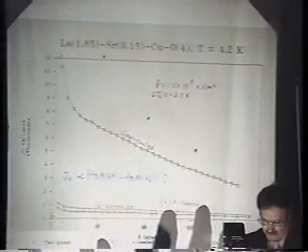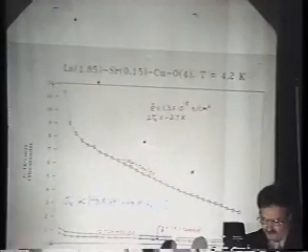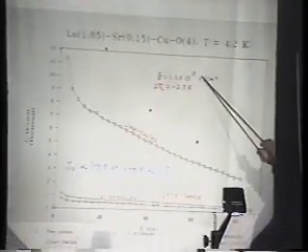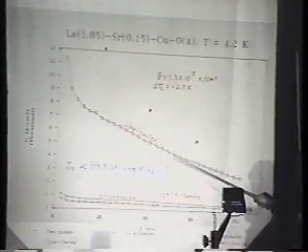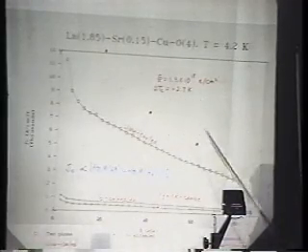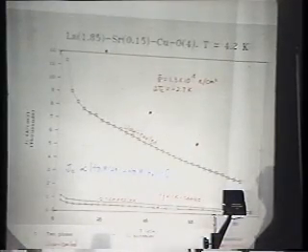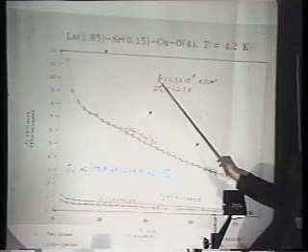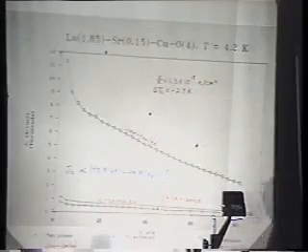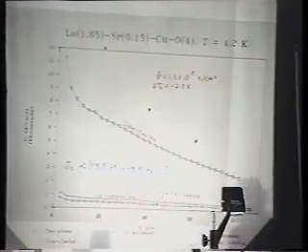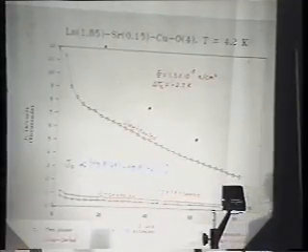Finally, I just want to make one brief comment. We have subsequently irradiated this slow-cooled sample with neutrons to a rather meager dose of 1.3 times 10 to the 18th, and we've seen an enhancement in the critical current density. However, at this very low dose, we've also seen a significant reduction in TC by about 2.7 Kelvin. These are very preliminary results, but perhaps very relevant.